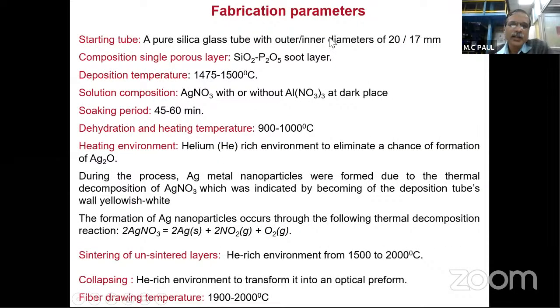We deposit a phosphosilica layer, with deposition temperature 1475 to 1500. Then we soak the layer in silver nitrate and also aluminum nitrate, soaking for 45 to 60 minutes. Then dehydration followed by helium. Then during precipitation, it gives rise to a sintering process, and at high temperature it gives rise to silver and nitrogen oxide. And we maintain a helium environment.